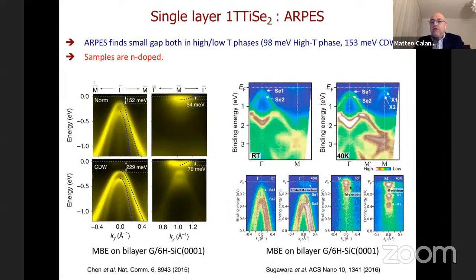Now, there have also been ARPES measurements, and the ARPES measurements are important because the system has an electronic structure that is not easily reproducible with the standard density functional theory method. I will show you in a moment. So if you look at the 1T phase, these two plots, there is at the gamma point 2 selenium bands that you can see sketched by the blue dots. And these 2 selenium bands are completely occupied, and they are 152 millivolts, maybe a bit less, depending on the estimate, depending on the measurement, below the Fermi level.